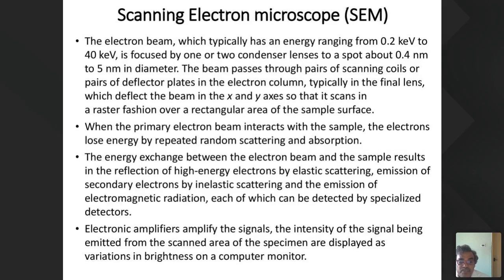Here the electron beam typically has an energy ranging from 0.2 kiloelectron volts to 40 kiloelectron volts, and is focused by one or two condenser lenses to a spot of about 0.4 nanometer. The beam passes through pairs of scanning coils or pairs of deflector plates, typically in the final lens, to deflect the beam in the X and Y axes so that it scans in a raster pattern.